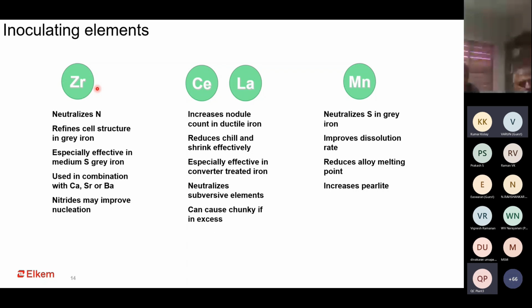Even if you have a pure magnesium treatment, without a ferrosilicon magnesium treatment, many foundries use rare earth based inoculants to reduce the effect of subversive elements, the elements which otherwise would have caused poor nodularity, for example titanium. So to control the effect of those elements, rare earth based inoculant can be used. But people have to be a bit careful with the addition rate of these rare earth elements, because a higher addition rate means you are introducing more cerium and lanthanum into the system, which can cause a tendency for chunky graphite in the castings.